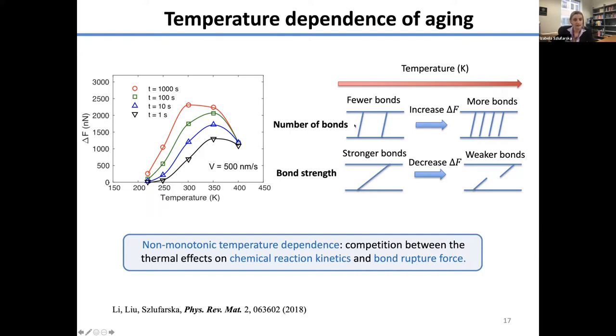One of them is that at higher temperature, we're going to bond the interface faster. So we're going to have more bonds because it's a thermally activated process. On the other hand, if there's a higher temperature, the bonds are weaker because once we start pulling on them, again, it's a temperature activated process, so it will be easier to break them. So we have this competition: at higher temperature, we have more bonds, but the bonds are weaker. And the balance of those is going to be different for different materials, but for silica it fell into this room temperature regime for maximizing aging.